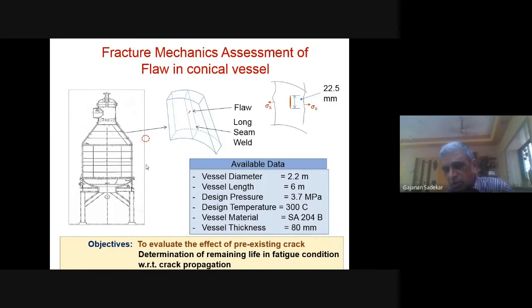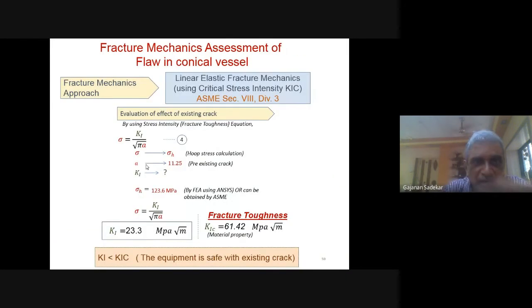and that crack was observed in the ultrasonic testing. Then the question became whether this crack will grow in operation. Then also people said whether this crack was originally existing. Anyway, our radiographic films were not showing the crack, but the crack was existing after 1.5 years. So they said, oh, you might have missed it. But anyway, what was decided was to carry out the analysis. And we carried out the linear elastic fracture mechanics calculations.